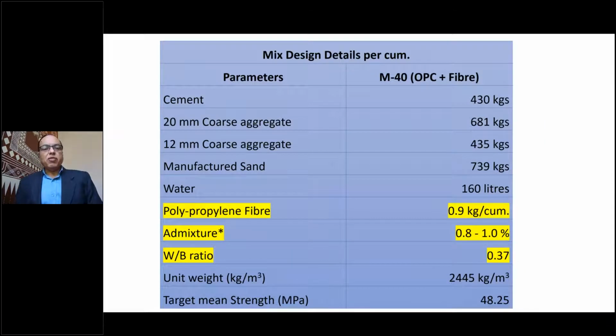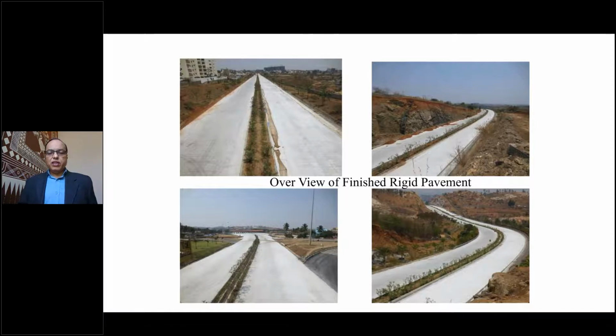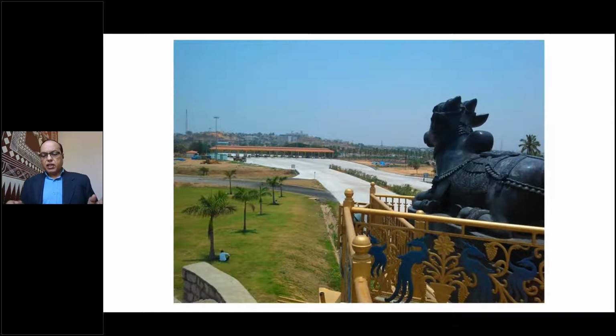Now, this was the mix design for that particular project. I just want you to observe some highlighted portions here. The first one I have already said: polypropylene fibers were used at the rate of about 0.9 kg per cubic meter. That is a small percentage of fibers that will help us to a great extent to reduce cracks. Admixture 0.8 is normally used. Sometimes we varied it up to 1%, and the water binder ratio was 0.37, and the target mean strength was 48, and what was achieved was much more. So this is the overview of the finished concrete pavement on NICE road. This is one more view of the finished concrete pavement.